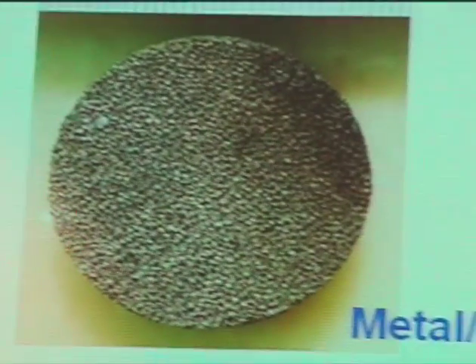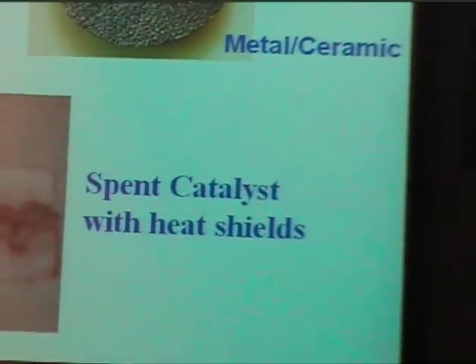So here's what some of these foams would look like with and without the metal, the nickel, on there. This here is the ceramic foam uncoated above and below the bed, and here's with the catalyst support. We would wrap the arrangement in a ceramic blanket and then slide it into the quartz tube reactor. That gave you a good fit, and you got minimal bypassing.